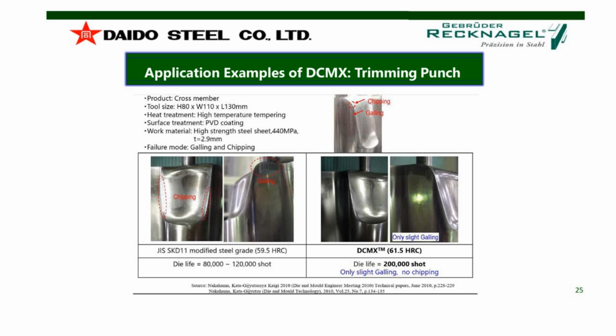This is also absolutely typical for D2 grade. The problem in this trimming punch was chipping at the cutting edge and also some galling above. The customer was using D2 with hardness close to 60 HRC with a tool lifetime of 80 to 120,000 shots. Then he used DCMX for the first time with a higher hardness, and he had no problems with chipping, just a slight galling, and the tool lifetime goes up to 200,000 cycles, and that's, I guess, very impressive.